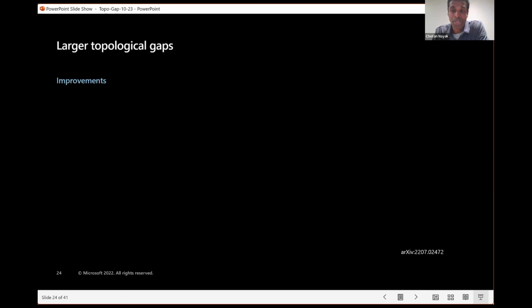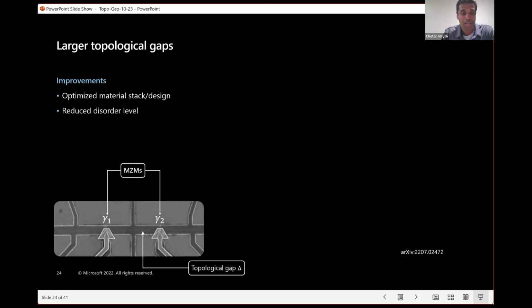We actually saw similar data in a number of devices. We took that understanding, made some improvements to get larger topological gaps. We further optimized the material stack and device design. We were able to reduce the disorder level a little bit. Here is one of these sort of second wave devices. One of the changes you can see is that whereas before we had split gates over the aluminum, here it's a single plunger gate, okay?